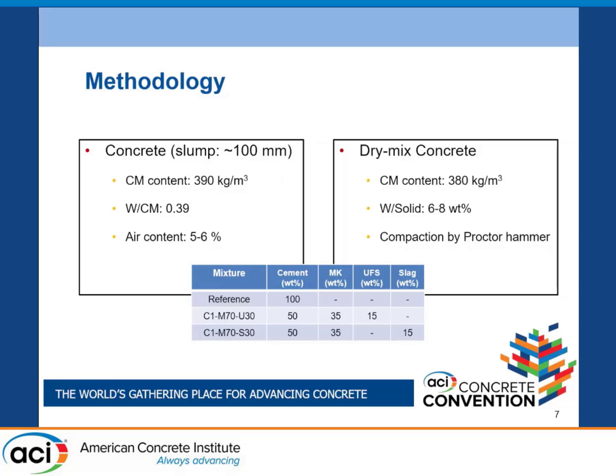For the binder composition in our study, the reference sample was 100% commercially available cement. The first sample with Metakaolin and UFS had, from the total binder weight, 15 weight percent UFS and 35 Metakaolin. We compared our results with the sample that has ordinary slag before grinding, with the same amount of Metakaolin and Portland cement.